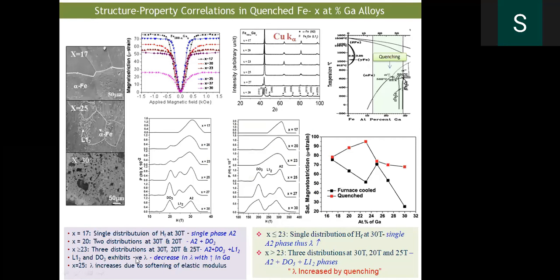First of all, as I told you, the microstructure is very important. The microstructure shows the presence of only a single phase, that is alpha Fe phase, for 17. But as I increase the composition, I could see other phases also coming into the picture. When I see the magnetostriction with respect to this, the magnetostriction is found to show a two peak behavior kind of thing. It is increasing and then it shows a decreasing trend. To identify what the different kinds of phases are,